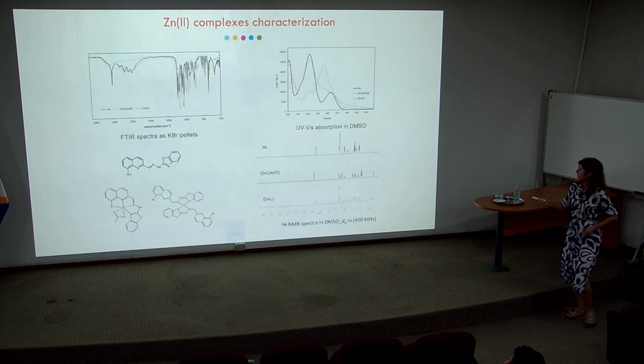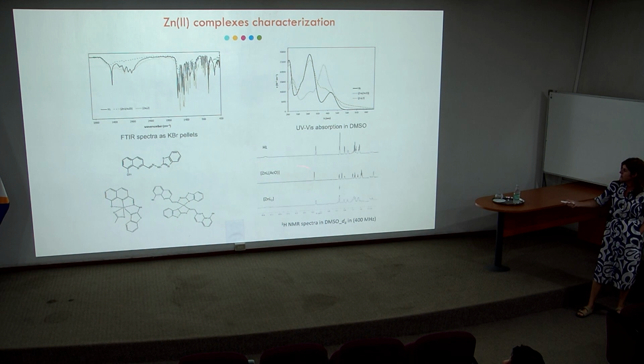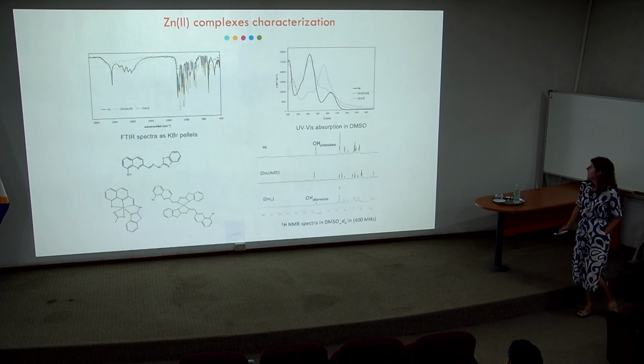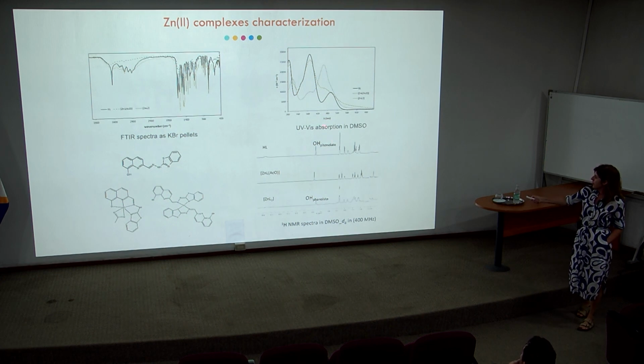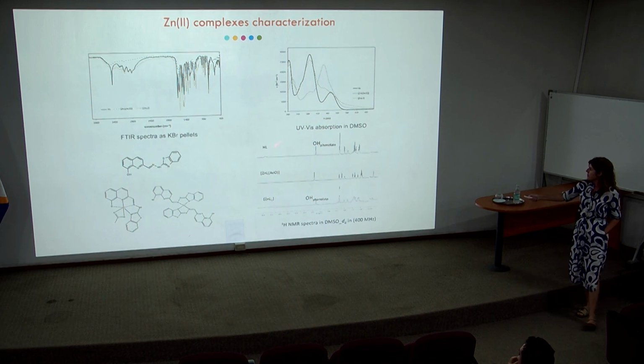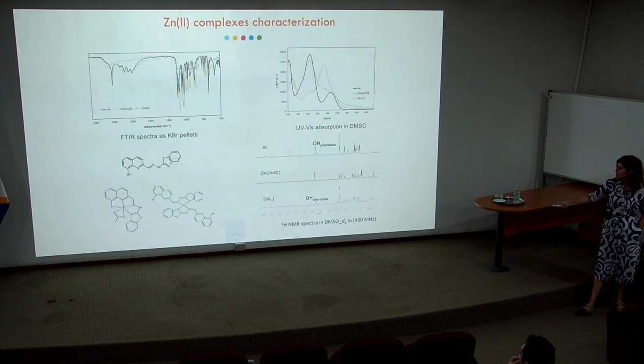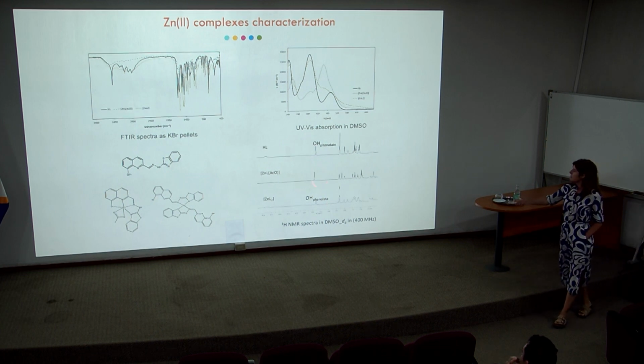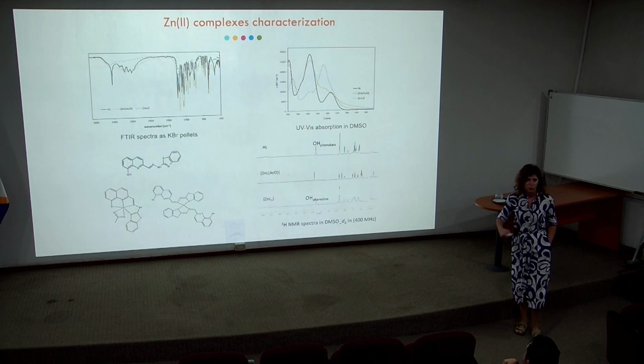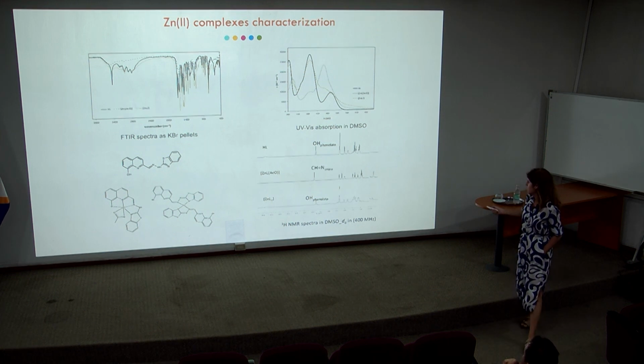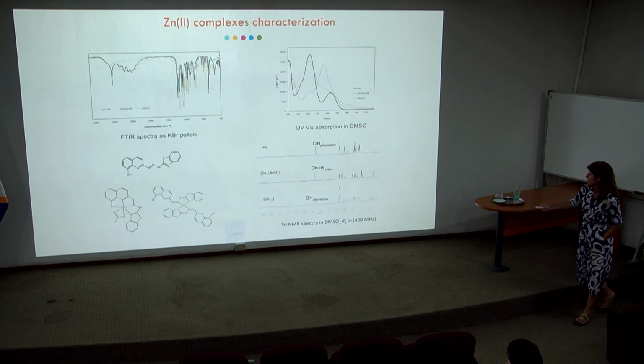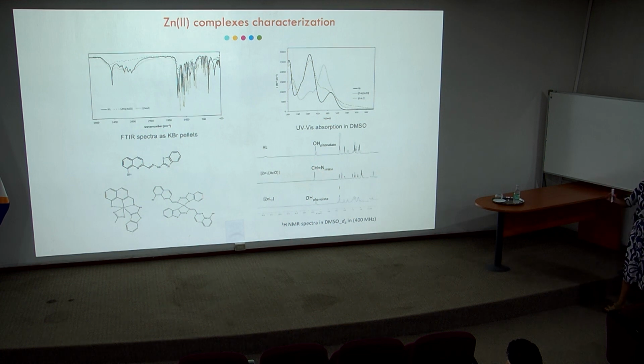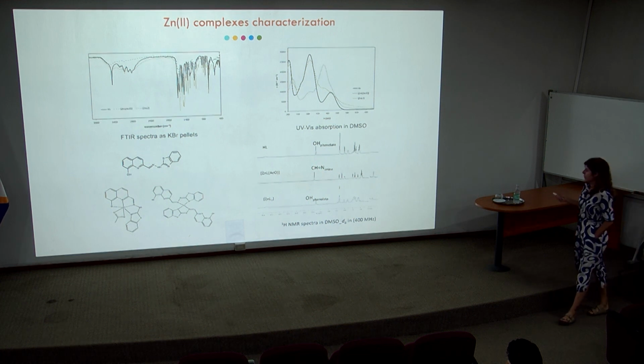For instance, here I show you the spectra of the ligand, the zinc 1-to-1 and the zinc 1-to-2 complex. And we can identify here the proton corresponding to the phenolate in the ligand and in the zinc L2. In the case of this one, this is not the proton belonging to the phenolate, but the proton from the imine, which appears in this range.